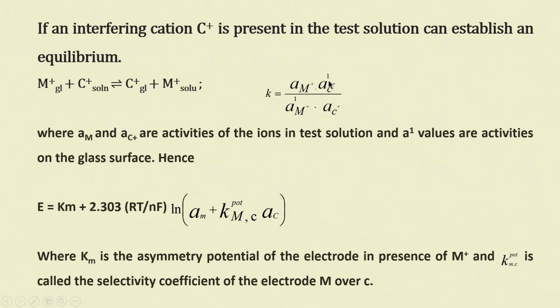Okay. So, here I am writing A1, now A1C and A1M. So, here it works out something like this, then I can write E is equal to Km plus 2.303 RT by nF ln (Am plus K^pot_MC times aC), where Km is the asymmetry potential of the electrode in presence of M+, and K^pot_MC is called the selectivity coefficient of the electrode, M over C.